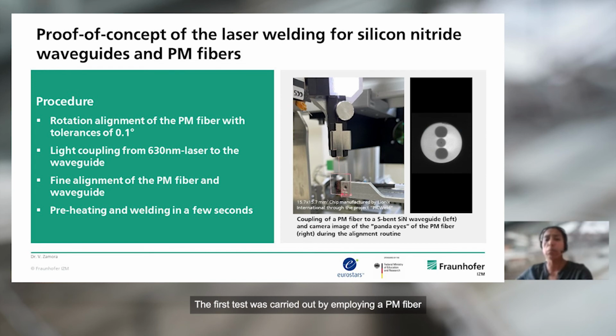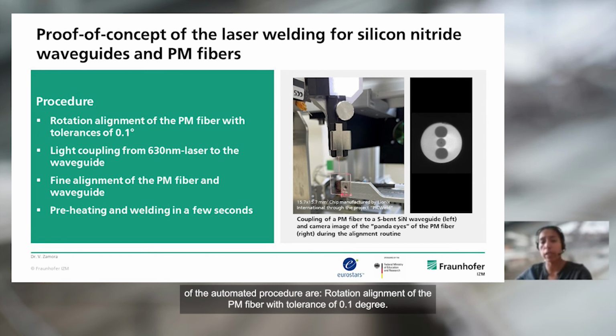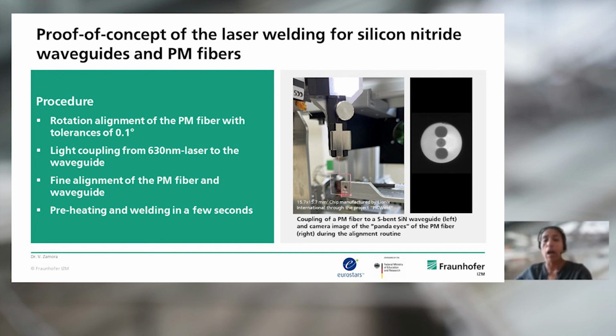The first step was carried out by employing a PM fiber and a reference silicon nitride waveguide on a fused silica chip. The main steps of the automated procedure are rotation alignment of the PM fiber with a tolerance of 0.1 degree, light coupling from a 630 nanometer laser to the waveguide, fine alignment of the PM fiber and waveguide, and preheating and welding in a few seconds. So, the first automatic routine shows that PICs can be directly connected. Here we see clearly that light is transmitted through the waveguide. However, there is still work to be done in order to define an optimal process in the recently installed machine.